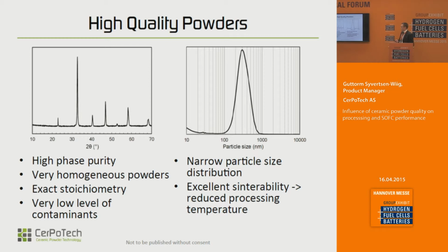So the materials have very high phase purity because we have very exact and good control of what we're actually putting into the furnace, and then we're getting it all out. The powders are very homogeneous because of the small particle size and the small reaction distances, making complete reactions quite easy. And the stoichiometry is very, very exact, and we don't really have any source of contamination except for our raw materials. That's also kind of driving the price. You can get as pure raw materials as you want if you're willing to pay for it.